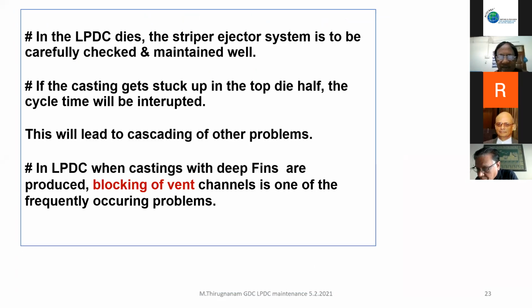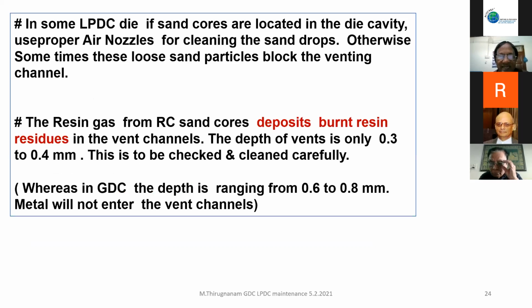In the low pressure dies, vent depth is very small, hardly 0.3 to 0.4 only. So if there is a minor block also, you will have a lot of problems. Fins won't form, you will have a lot of misruns and the casting will not be in full form. If they are using a lot of gas cores, the resin gas and sand cores will deposit burnt resin gases and resin on the vent channels. If this gets blocked, with hardly 0.3, 0.4 depth, and it becomes 0.1, 0.2, there will be a lot of cold shuts and all that. So cleaning in the low pressure die casting dies is very important. Whereas GDC is not that critical. If 0.6, 0.8 mm is there, you can still get away with 0.5. Nothing happens.